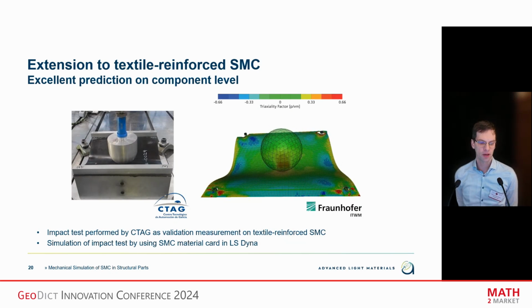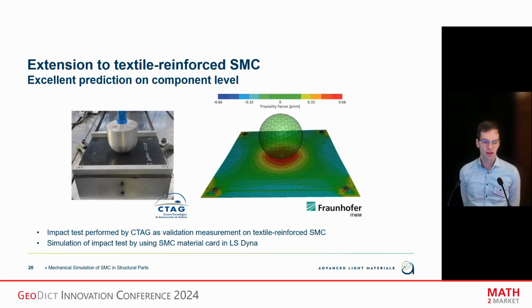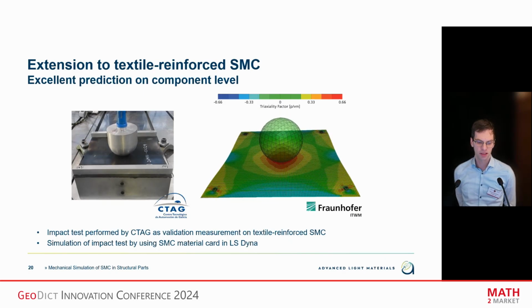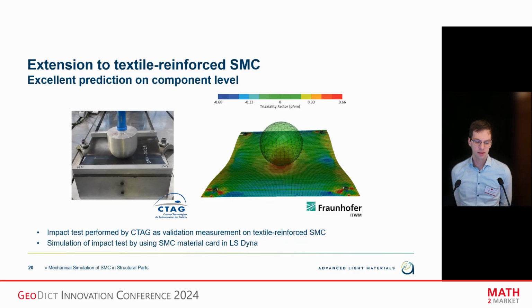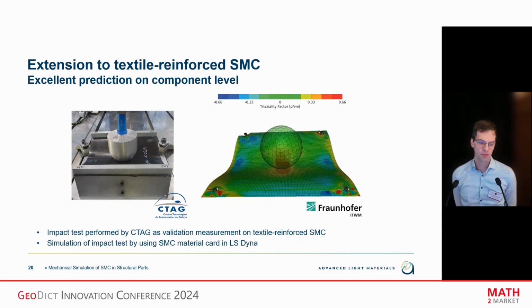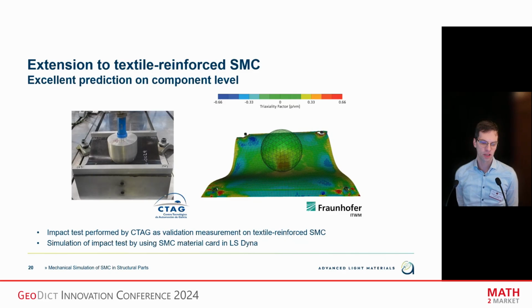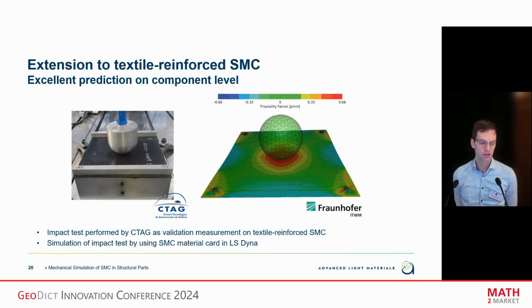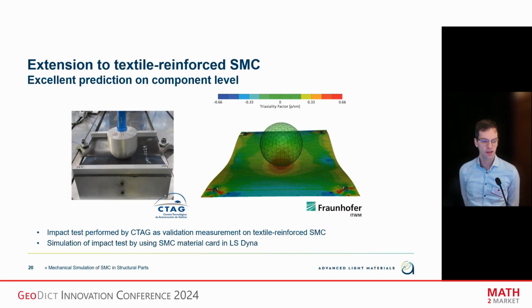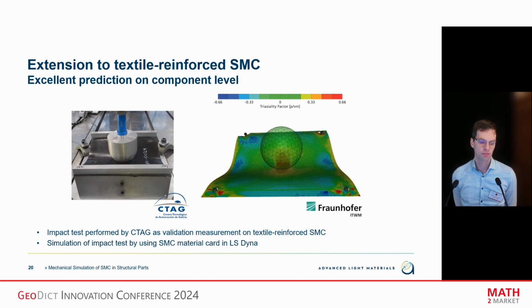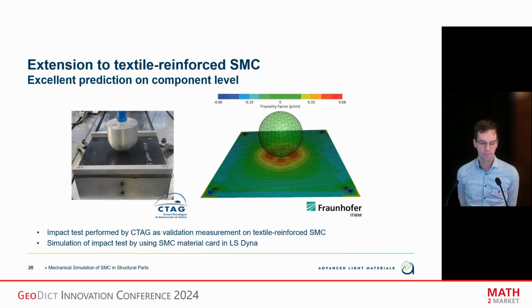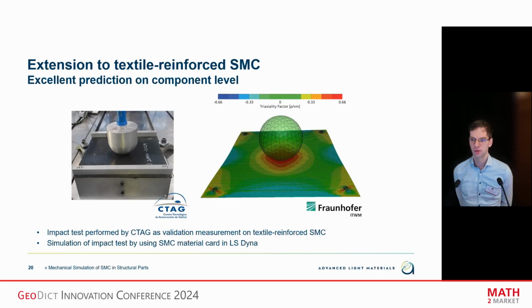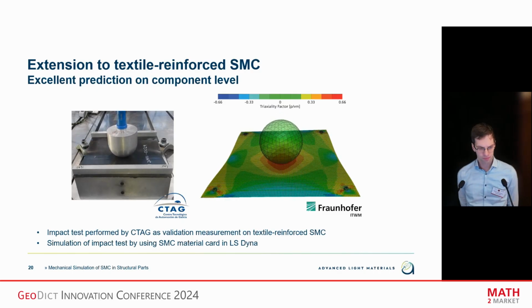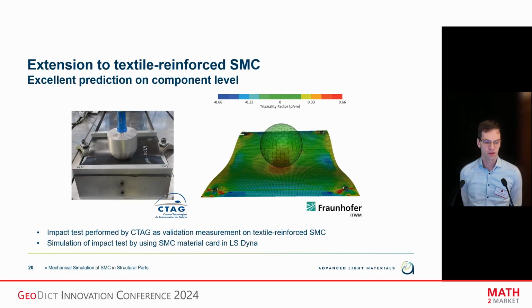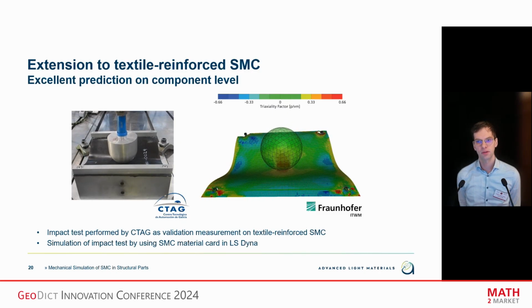a validation experiment performed by our project partners, and you see here on the left the experiment and on the right the simulation in LS-Dyna with our material card. And I think you will agree that the prediction of the simulation is really accurate. So we have the failure at the screws, but there's no failure in the middle where the impactor is, and this is perfectly predicted also by the LS-Dyna simulation.